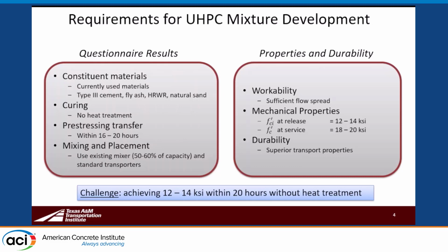And then mixing and placement. Some of the items we looked at: recently PCI has been sponsoring a project on UHPC and working with precasters, and one of their recommendations was to use about 50% of the mixer capacity to ensure there's enough energy to actually mix the UHPC, which is required. We also looked at properties and durability requirements, such as sufficient flow spread needing to be maintained. We looked at some values in the literature initially for that.